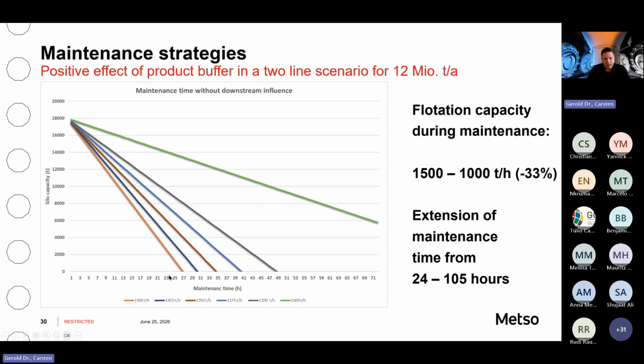And to show you what happens, it depends on how much you want to reduce your flotation. The normal case would be 1,500 tons. But if you reduce it basically to 1,000 tons, so you reduce the capacity in flotation by 33%, you could basically run maintenance for a very long time. But this is a thing where I really see a benefit in dry processing or dry grinding.